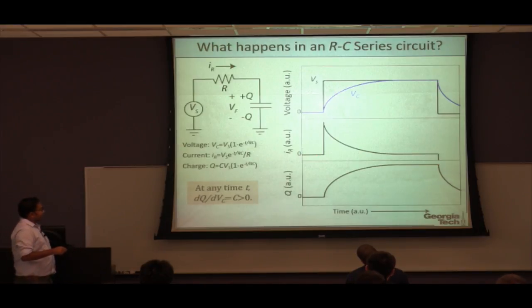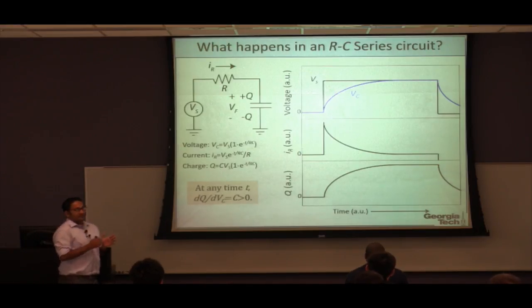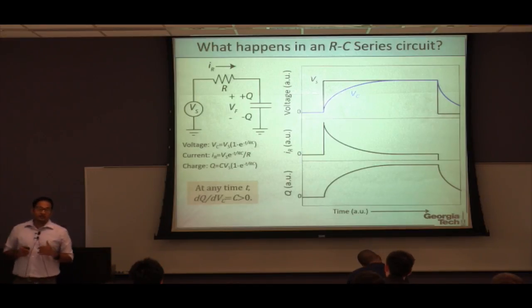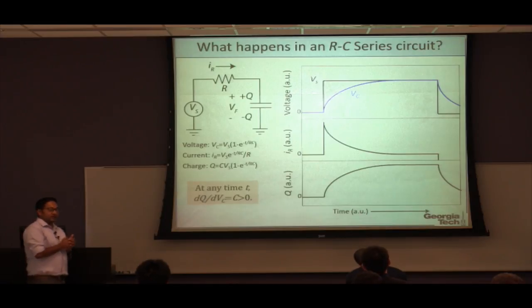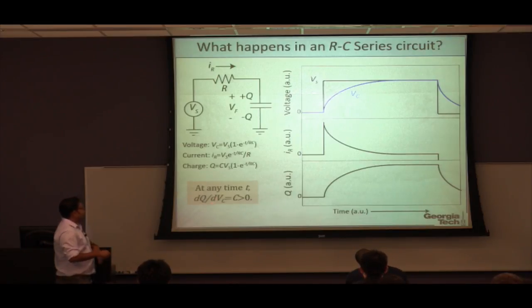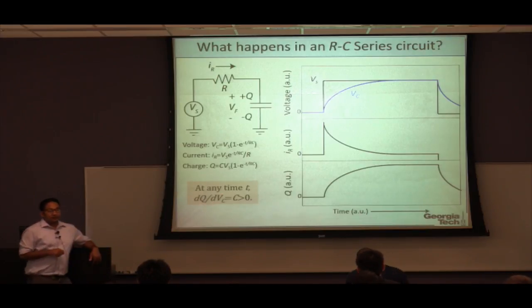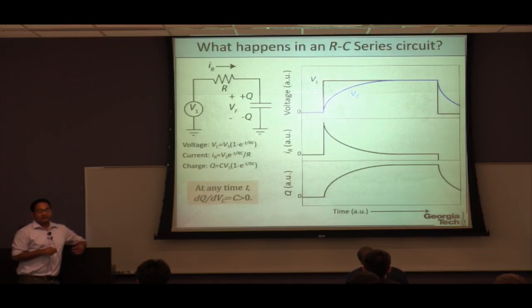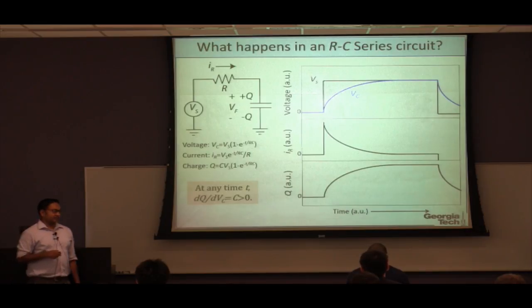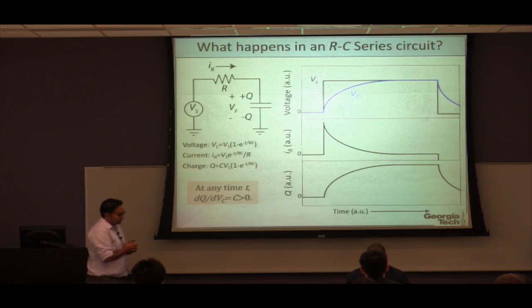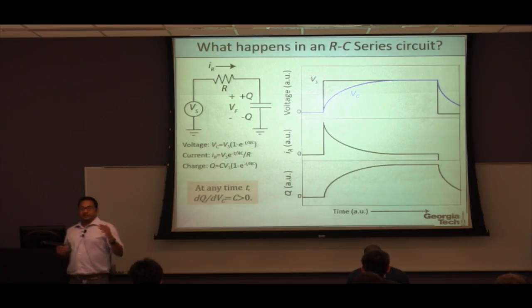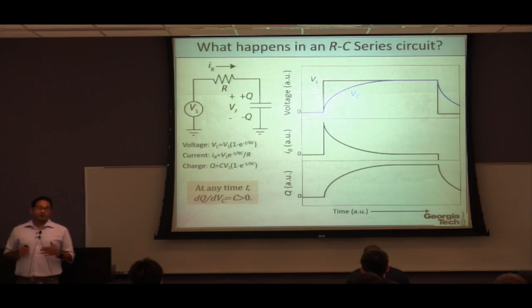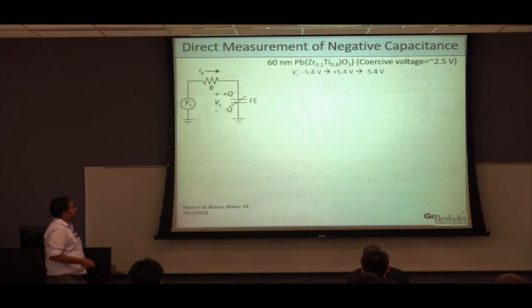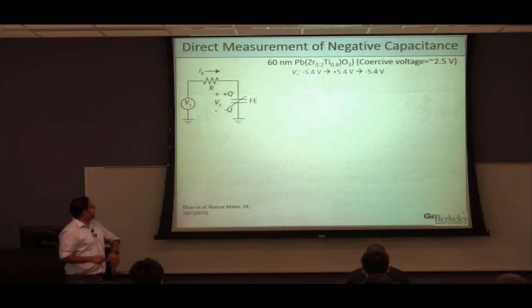The important thing to note here is that if we take any time step delta T and measure the change in the ferroelectric voltage and the change in the charge across the ferroelectric, and take the ratio of this, we'll see that this ratio is a positive number, and it is equal to the capacitance of the capacitor. So in other words, in a regular RC network, the change in the charge and the change in the voltage will be in the same direction. With that, let's look at the experimental results.